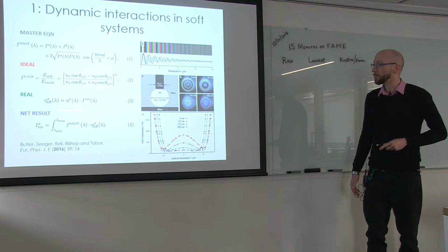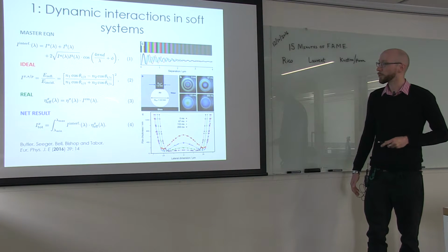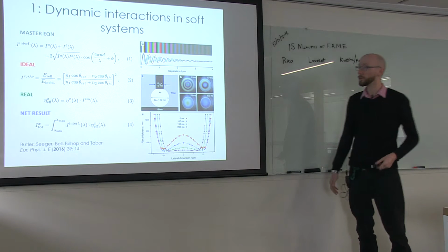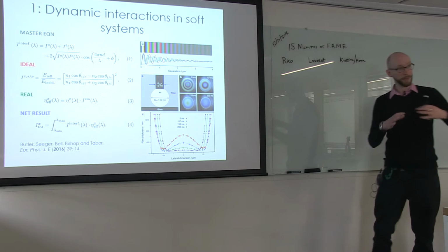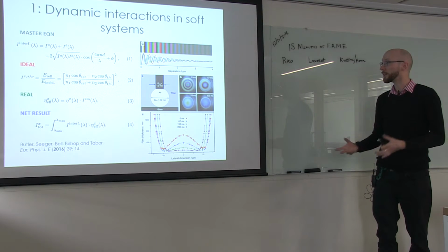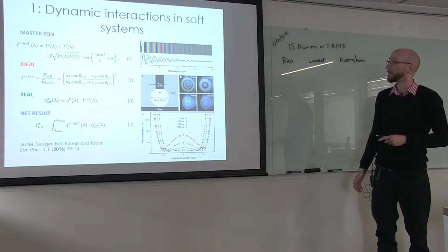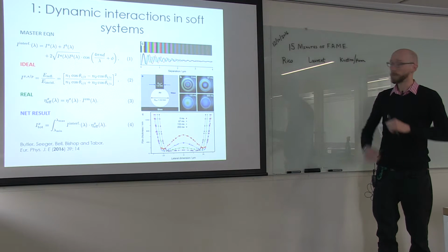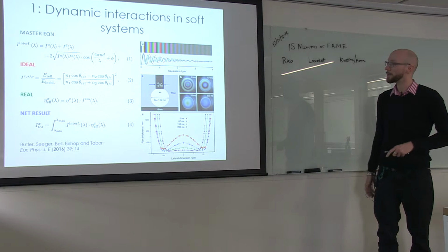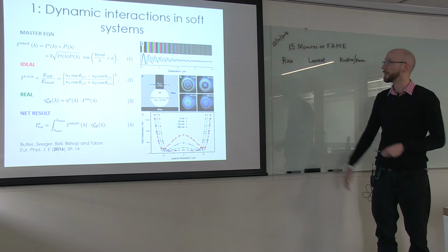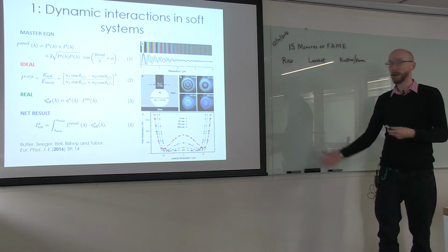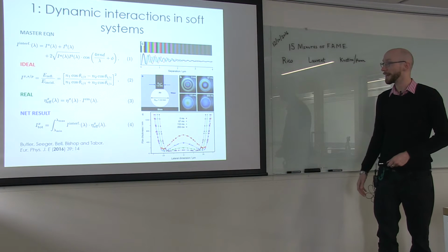And the major advance we made in understanding this problem was to say that in real systems, if you're using a real camera like this camera here, then the sensors in the camera, the different color sensors, have different sensitivities to different wavelengths of light. And if you account for that, it explains why you start off with these beautifully resolved colors for very thin separations, for really thin films, that even out to grey as you go off into space. And you've probably seen this phenomenon in refraction and interference in your daily lives.